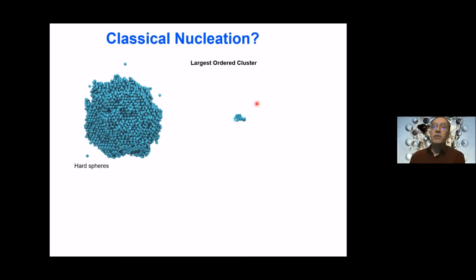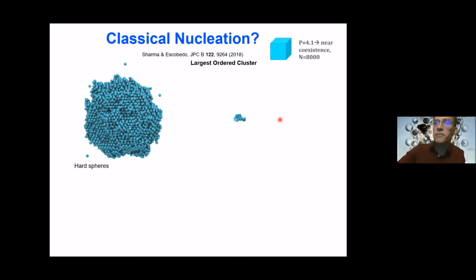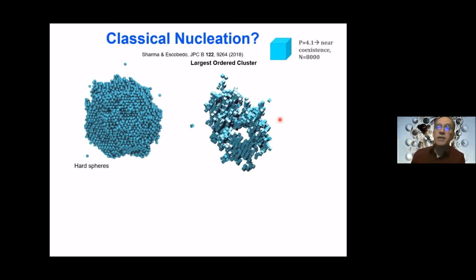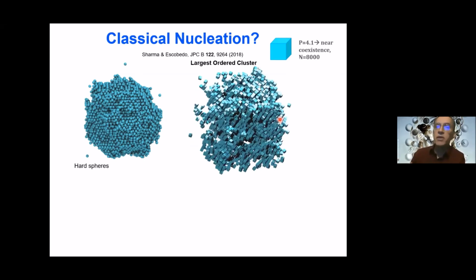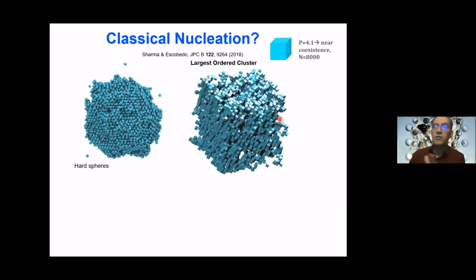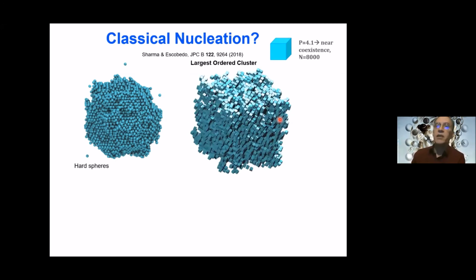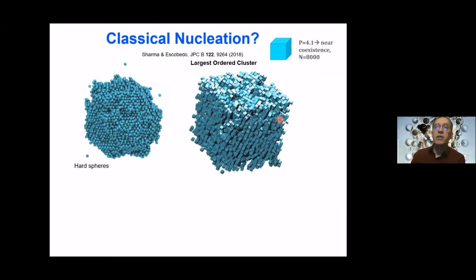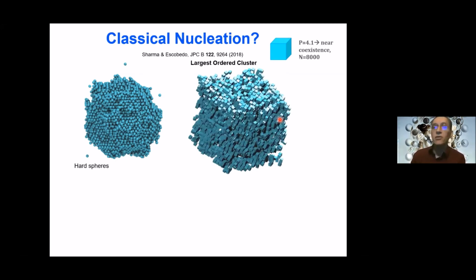Well, if you try to do the same thing for the case of cubes, you won't see that. You basically see small nuclei forming all over the place, coming and going, and eventually they consolidate into a larger cluster. So it looks a bit like a spinodal decomposition, but it's not, because it also happens when you have large free energy barriers.